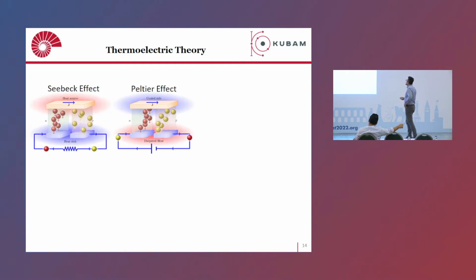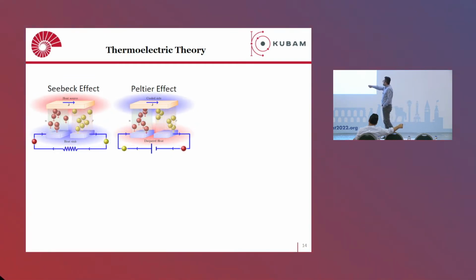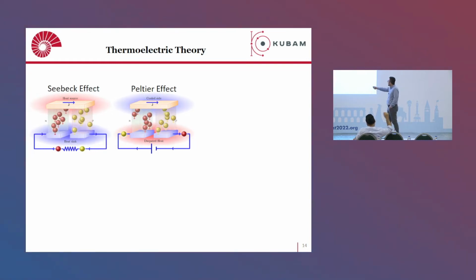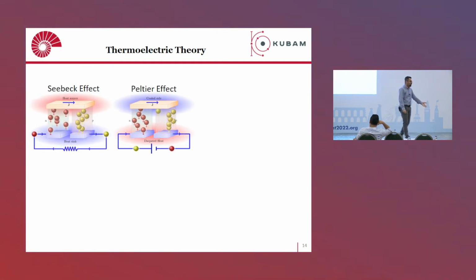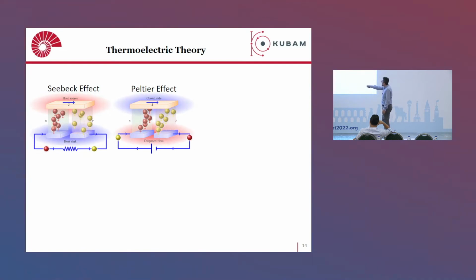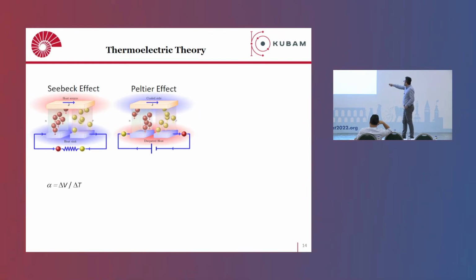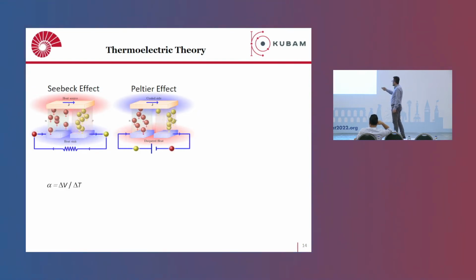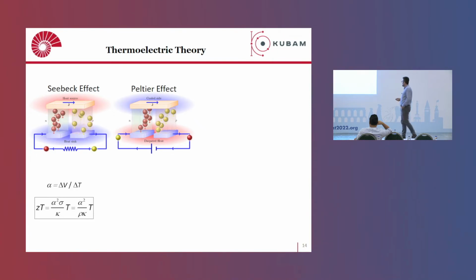So here is the thermoelectric theory. These are based on the Seebeck effect for power generation and the Peltier effect for cooling. Here we have n- and p-type semiconductors. If we create such a circuit and apply a thermal gradient, this produces voltage because we force the charge carriers to move from the hot side to the cold side, similar to gas molecules, for example, and this creates a potential difference. The potential difference that you create per temperature gradient is called the Seebeck coefficient. For the same circuit, instead of applying the temperature gradient, if you apply current, then you create a temperature gradient, which means you can use it as a Peltier cooler. This part will be cooled, this part will be heated. You can dissipate this heat with some methods.